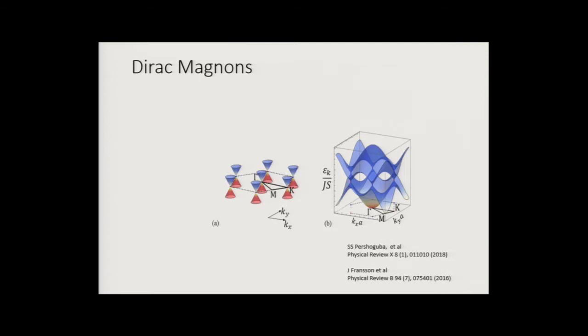This is an example of the chromium trihalides, where it turns out that there is a Dirac crossing point. At low temperatures, you do have a conventional quadratic dispersion for the ferromagnetic mode, but at high energy, you have this Dirac crossing point that couldn't be sampled. So the difference for the fermions and bosons is that I can live near the chemical potential and put the chemical potential near the Dirac point for fermions by biasing it or by gating, for instance, my structure.